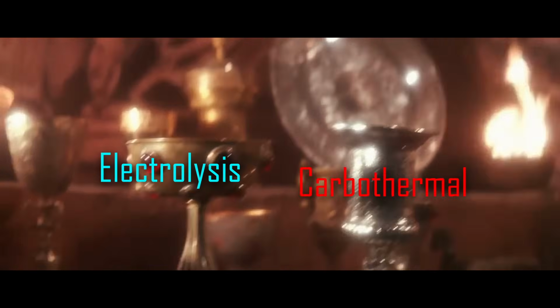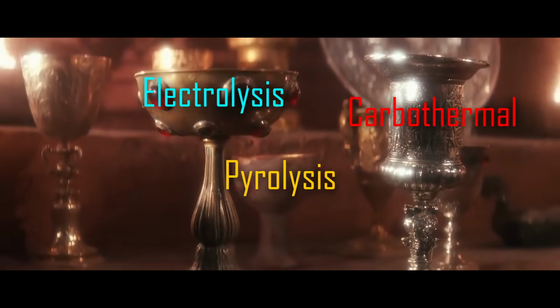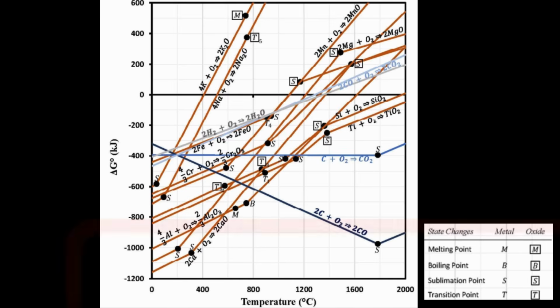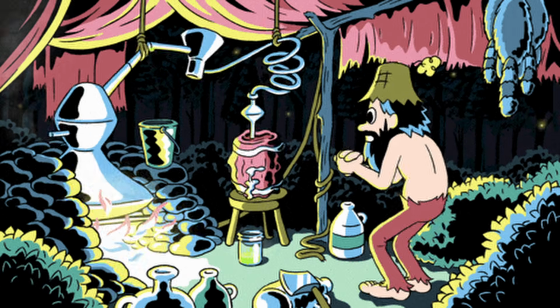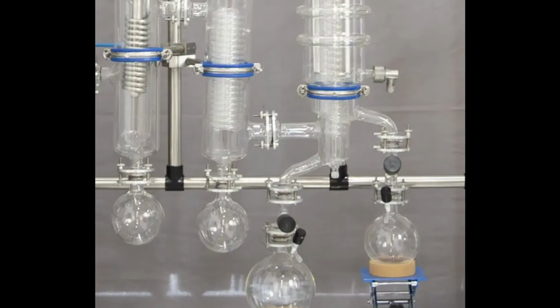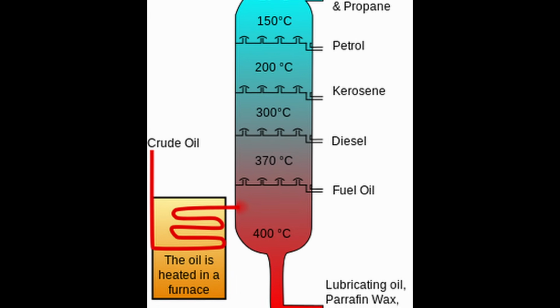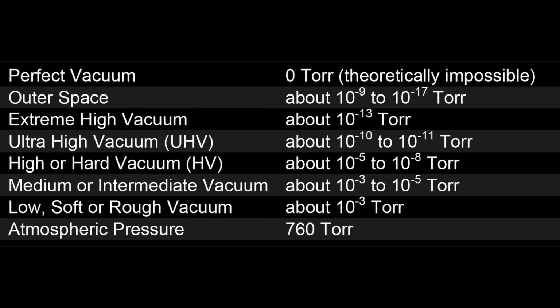In other words, we can selectively reduce oxides based on temperature. In my opinion, pyrolysis is the holy grail of astrometallurgy. The idea here is that in a vacuum, we can sublimate the oxides by just simply setting the temperature, and then we can condense the elements and the oxygen separately using different cold temperatures according to their condensation points, like a cold finger or a distillery, or molecular distillation for you lab rats, or fractional distillation for a more industrial scale of vision. The stronger the vacuum, the lower the temperature required to sublimate these oxides.